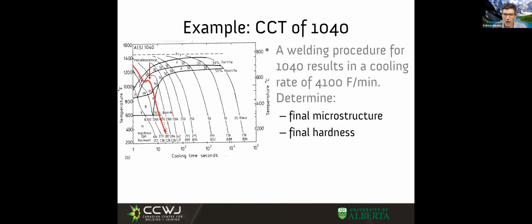So I have austenite. Austenite is the gasoline in my car. As long as I have austenite, I'm transforming. So until I finish transforming, I always have some amount of austenite, at this level of simple alloys we're discussing, right? So we have only austenite at the beginning, then austenite and primary ferrite. Now, austenite and primary ferrite and carbides, this cementite. Now that we discussed what phases we have, I want to know what microstructures I'm going to see. What type of microstructures would I see at this point that is marked in the diagram?